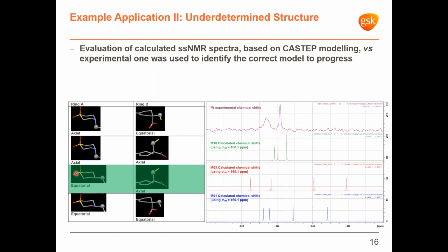So as next step, calculation of chemical shieldings in CASTEP was used to simulate solid state NMR spectra for each of the three likely structure solutions, M10, M03, and M01. And M10 with both independent molecules having ring A axial and ring B equatorial was identified as the most likely solution over the other two and progressed into final refinement based on the solid state NMR assessment. And you can see the related solid state NMR trace in green is the closest match to the experimental solid state NMR spectrum at the top.